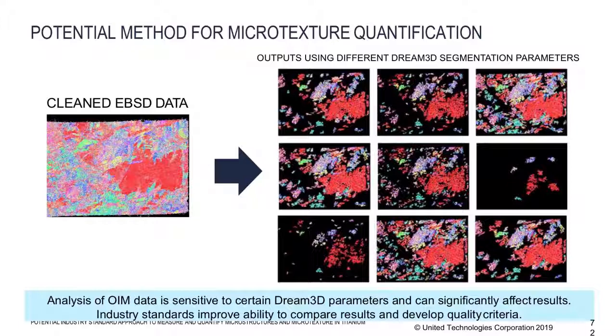So the other thing, we talked about those two key parameters, this orientation tolerance, how aggressively you want to group the pixels, and the minimum size. So if you vary those two, what would your output look like for this one sample? And you can see, you can make MTRs disappear, or you can make it pretty much be 100% MTRs for this one particular dwell sample.